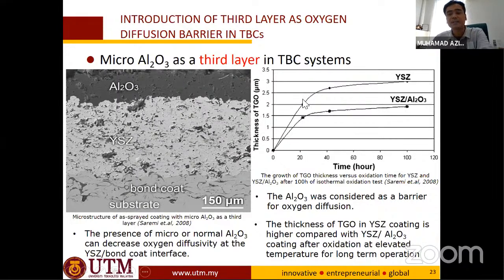So you can see this, the thickness will grow. For example, if we observe on a microscope, we check, it can go up to 3 microns. But if you have 2 layers, or a bilayer, with YSZ and at the same time alumina, you can see here they can reduce up to 50% of the thickness. So it's good to have another layer here to reduce the formation of thick TGO, or thick alumina layer, which is considered the barrier.